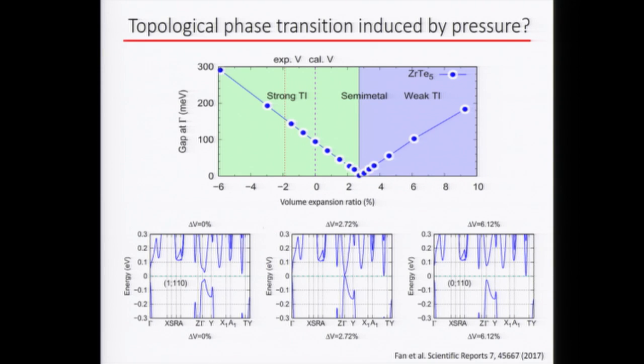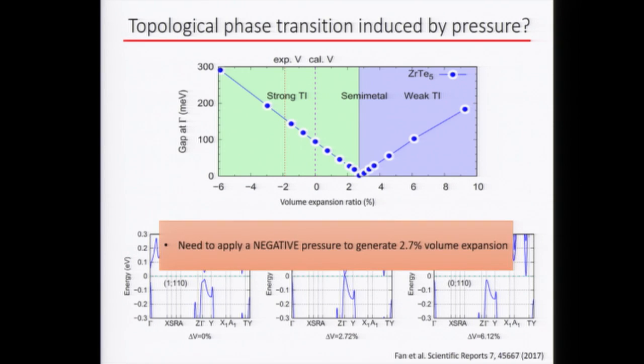Negative corresponds to pressure, and positive corresponds to negative pressure. Their conclusion is that the ground state is in the strong topological insulator regime, and you have to apply 2-point-something% negative pressure to go across the topological phase boundary. First of all, this is a large strain, by the way, 2.7%, and it's negative isotropically. There's no way you can do that experimentally.